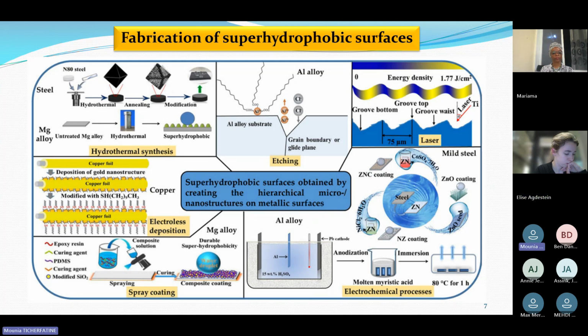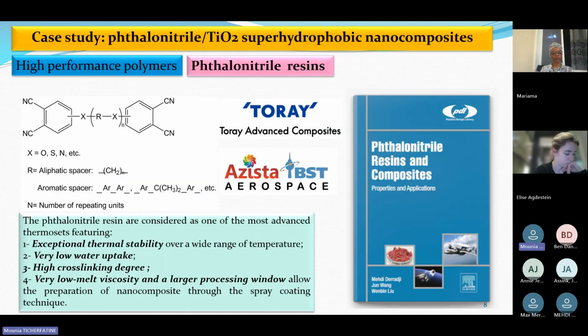Let's now move on to the specific case study we performed recently. As I stated in the previous slide, the nanocomposite spray coating can be seen as the most adequate and cost-effective technique to achieve superhydrophobic coatings. In this case, a new nanocomposite was developed from a high-performance phthalonitrile resin and surface modified titanium oxide nanoparticles. The phthalonitrile resins are considered as one of the most advanced thermosets, featuring an exceptional thermal stability over a wide range of temperature, a very low water uptake, a high cross-linking degree, and most importantly, a low melt viscosity and large processing window, which allow the preparation of nanocomposite through the spray coating technique.